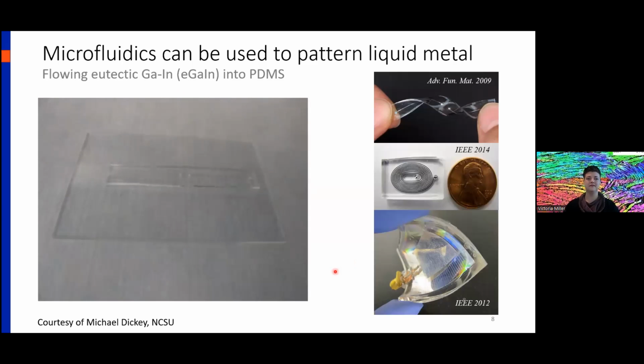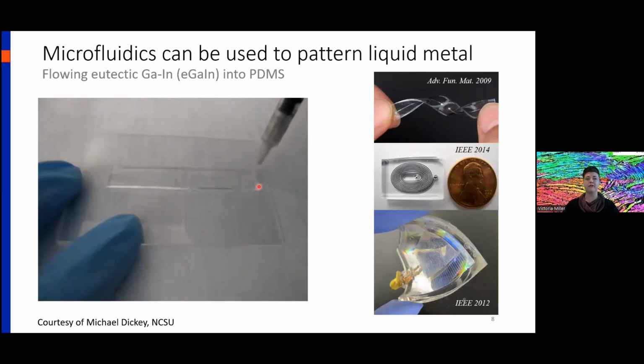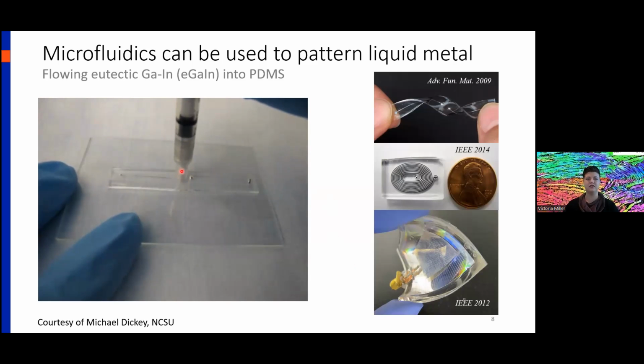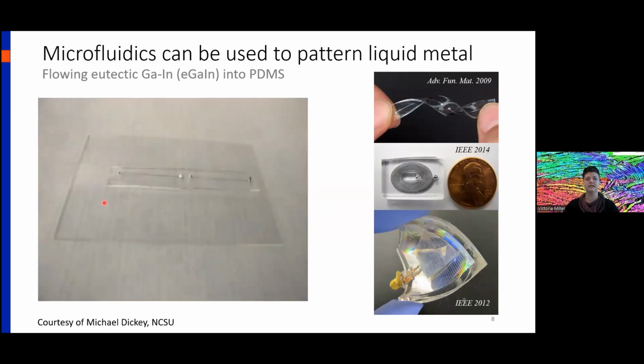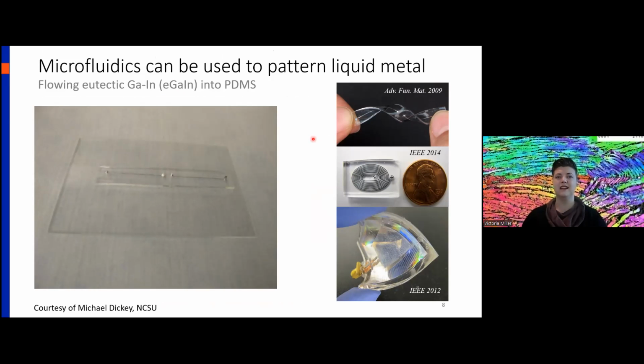Additionally, you can go ahead and use microfluidics to pattern these liquid metal electronics. So this is liquid eutectic gallium indium, and this is just PDMS with microfluidic channels built in. And you can see that this student is using a syringe to fill the channels. And once the channels are filled, you have this completely flexible, stretchable device. You can fill complex shapes like spirals. And then this down here is actually a flexible thermoelectric device.